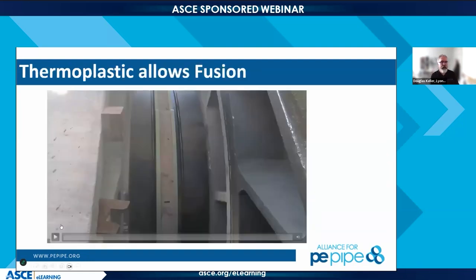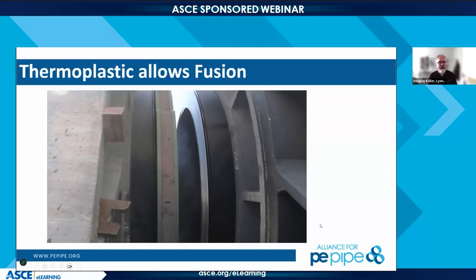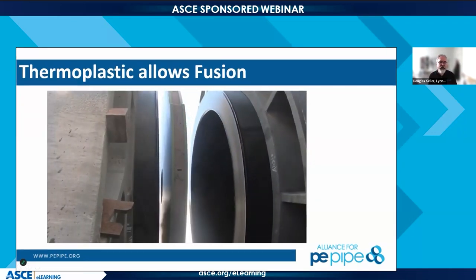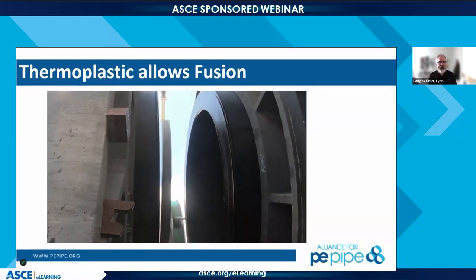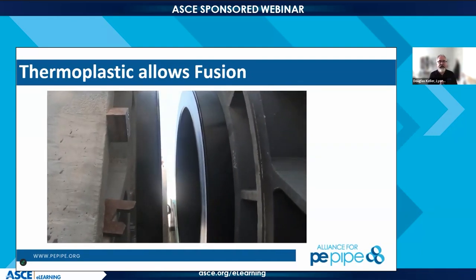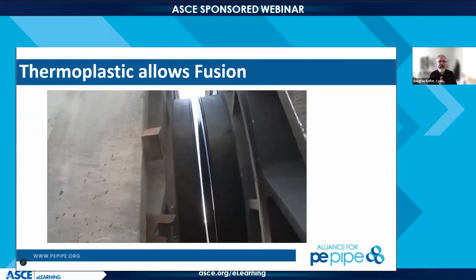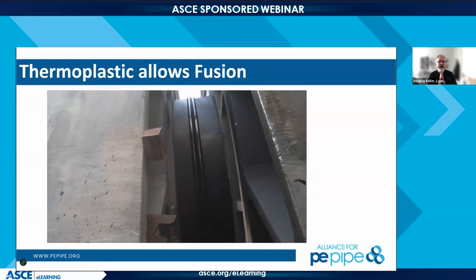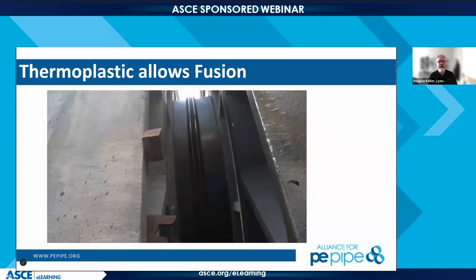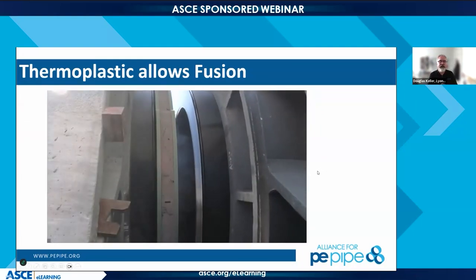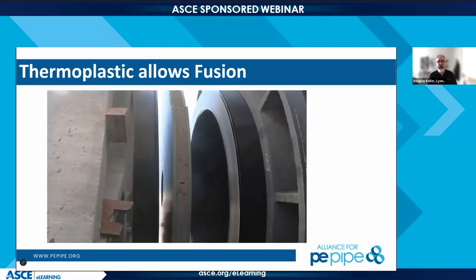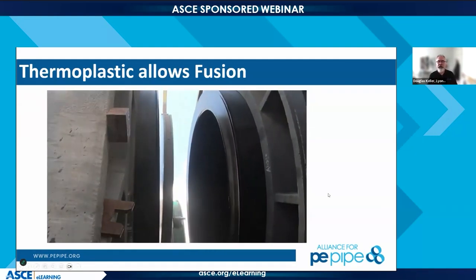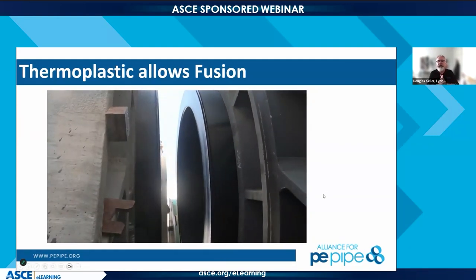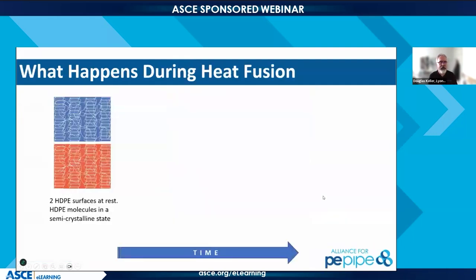Next slide. So this is a video of the fusion process. Here we've heated the material up, we've created a bead. We're removing the heater plate, and now we're bringing the pipe ends back together, and you're going to see the fusion bead form. See how that material is flowing up and out, and on the inside it's flowing out and down to form the fusion bead. So this is what can be done with a thermoplastic material that can't be done with a thermoset material. Now, I don't recommend quickly removing the bead like they did in this video. There is a cooling step and things that we have to go through, but it's that thermoplastic property that allows fusion to occur.